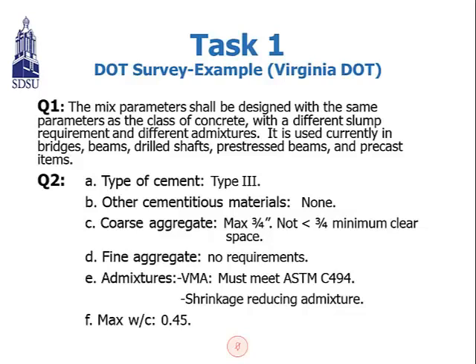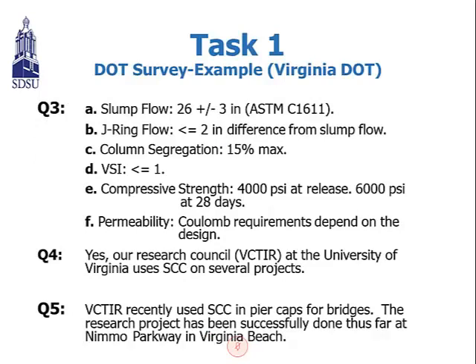And they allowed to use the type 3, and they didn't use other cementitious materials, and they used the coarse aggregate maximum 3/4 inches, and they don't have any requirement for the fine aggregate, and they used the VMA, which is a viscosity modifying admixture, and they must meet the ASTM C494 and shrinkage reducing admixture, and they also limit the maximum water cement ratio to 0.45. Also Virginia DOT limits slump flow to 26 inches plus or minus 3 inches and follows the other limits of the material features, such as J-ring flow must be less than or equal to 2 inches. And you can see other information for the requirement for the SCC mixtures.